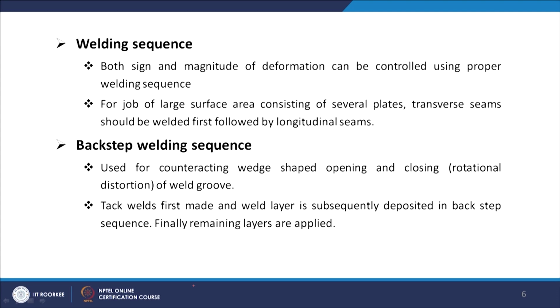and that also depends upon the welding speed. If your welding speed is low, in that case the spacing between tack welds has to be small. So, if you are moving at a slow speed, the spacing between the tack welds should be smaller. Then the first weld layer is subsequently deposited in the backstep sequence. So you are moving in the backstep. This is the welding direction. You move in that backstep sequence from the tack weld at one end to the opposite end.